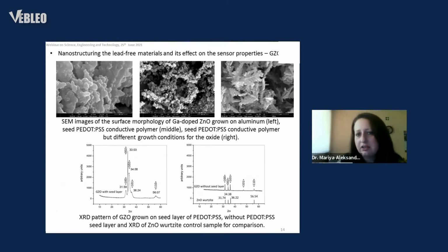Another approach that we used is to realize heterointerfaces, growing ferroelectric oxide not over a conventional metal electrode, but over an electroconductive polymer, which serves like an amorphous seed organic layer. As a result, the growing gallium-doped zinc oxide here for this experiment possesses a nanodendrite, nanoporous structure. If we decrease the content of gallium and get close to the pristine zinc oxide, these dendrite